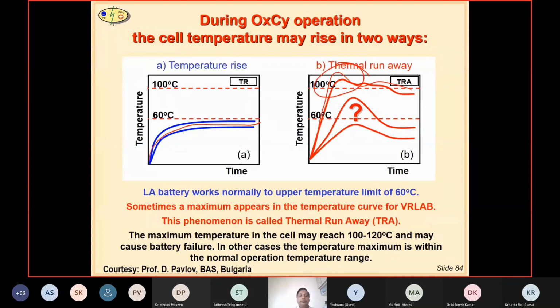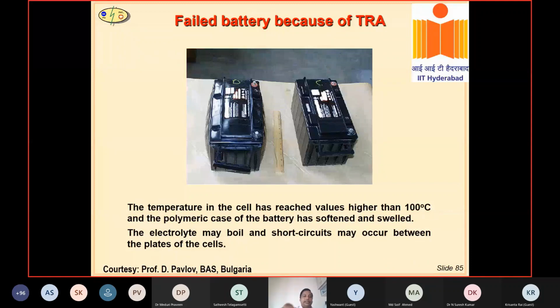I'll show you Professor Pavlov. I have seen his lab. You see, the lead-acid battery becomes like this, and it's very dangerous. Then what will happen? It may burst, and acid spillage can happen. And of course, it may not cause severe injury, but it can cause explosion. I remember once we were testing a battery, and the battery went even 3 feet, like 5 feet high, and then fell down. It can happen. I remember those days during PhD. This thermal runaway in lead-acid battery can be avoided.